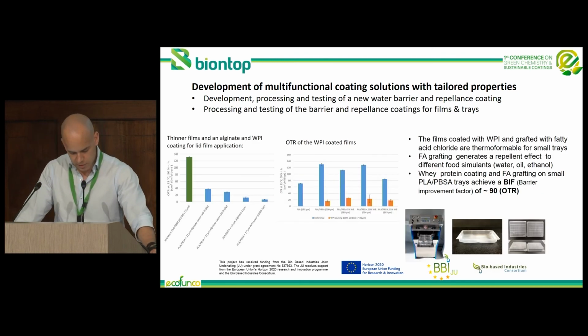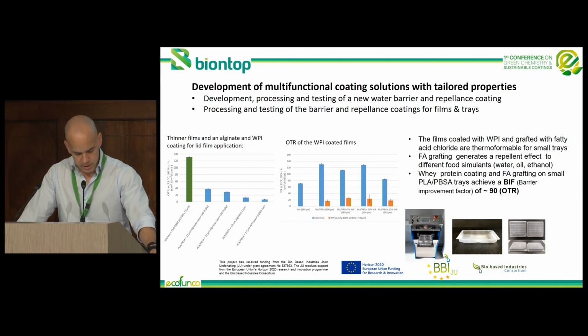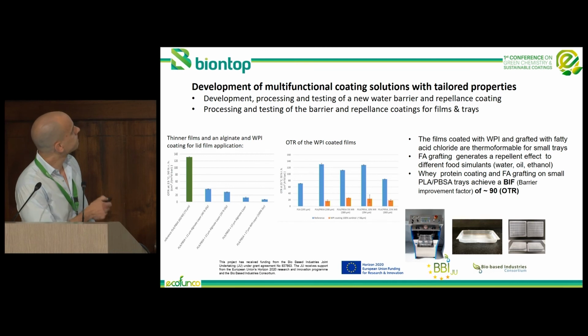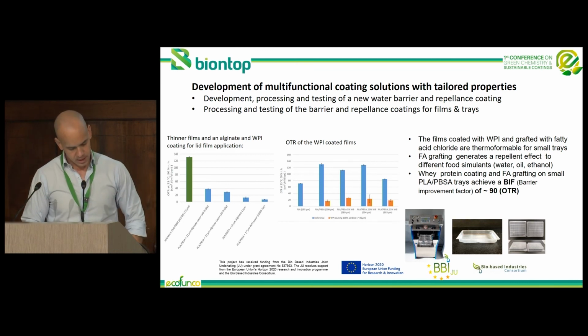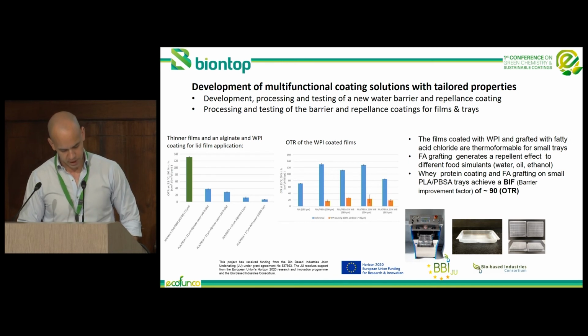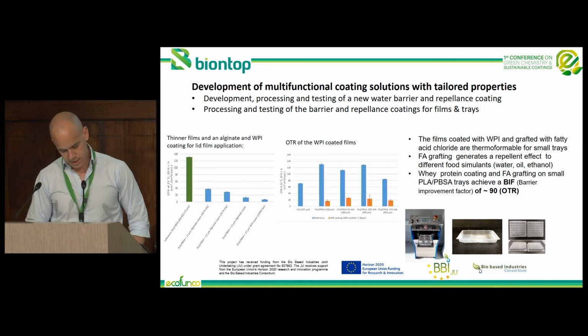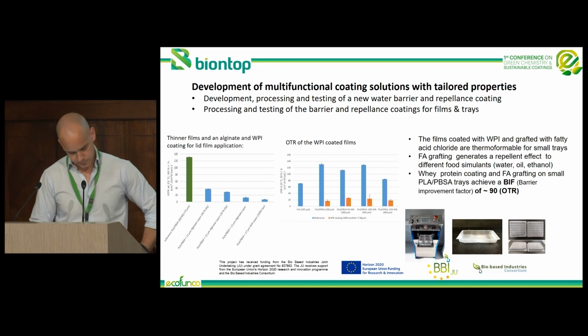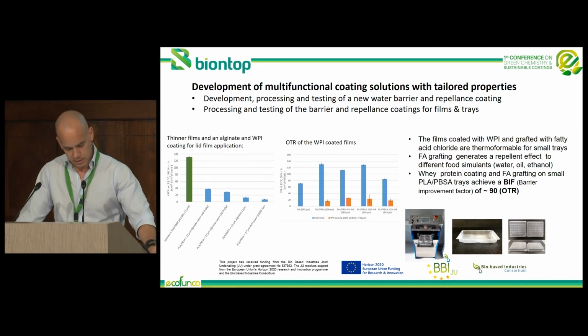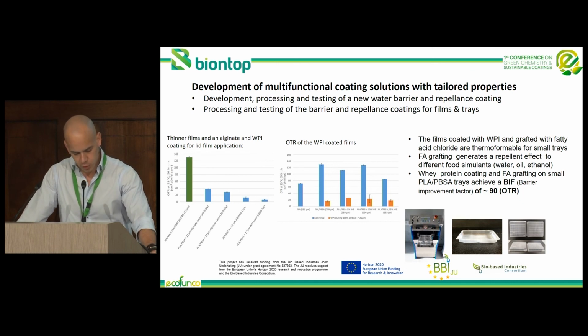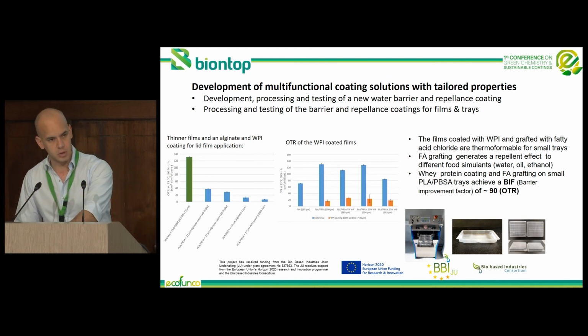In second place, we are processing the barrier and repellence coatings for films and trays for improved performance and scalability. The left diagrams here show thinner films and an alginate and whey protein coating for lead film application. And in the right diagram, you can see the oxygen transmission rate of the whey protein coated films for our trace demonstrators. As you can see, we have reached great improvements in barrier properties, but I also would like to highlight that we are using process modeling and simulation in steps like the protein denaturation and the drying stages as a supporting tool to improve performance, upscalability, and also to study the effect of the different steps in the coating development.